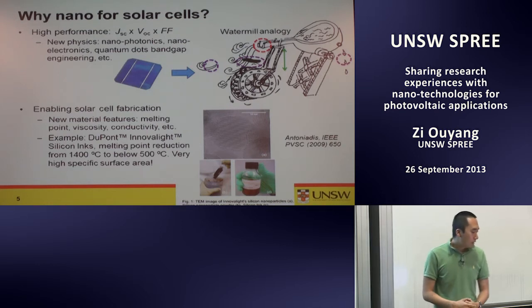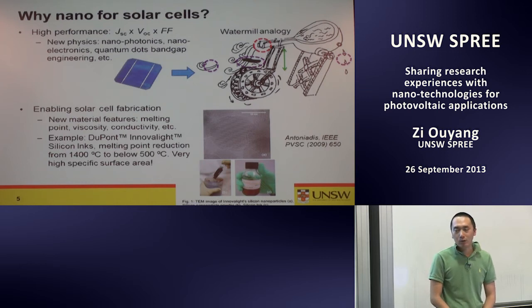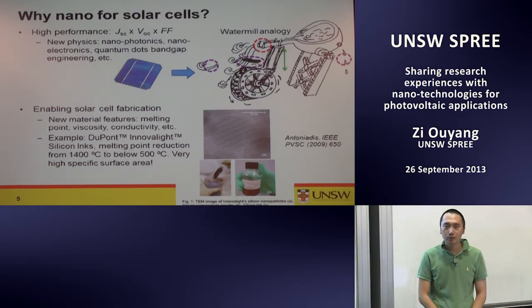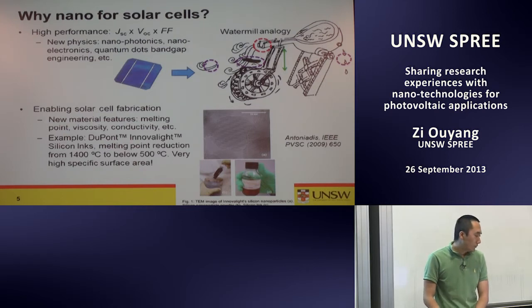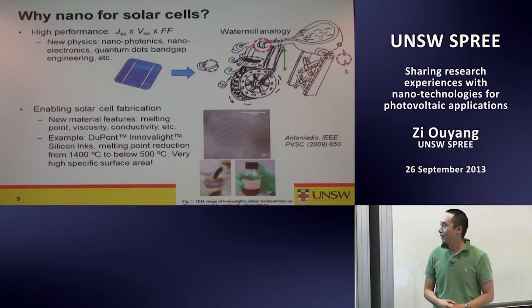So what they do is they have doped silicon in the ink, and they want to have the ink applied on the undoped or lightly doped solar cell to make a local high doping area. But if you think about the normal silicon material, like a bulk, it has a melting point at 1400. So it quite limits the process of applying that on a lightly doped silicon.